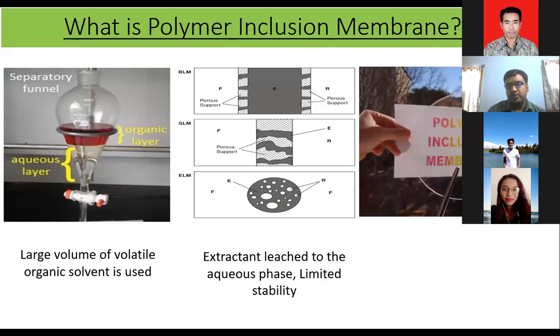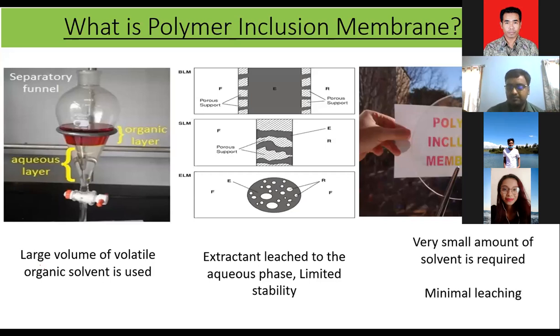When we move from this to the liquid membrane, we can minimize the use of organic solvent, but the issue here is the leaching of the extracting agent. That's why we cannot use it for a long time. But with the polymer inclusion membrane, we can minimize the leaching of the extracting agent, and we also use a very small amount of organic solvent. So that was the part about polymer inclusion membranes.